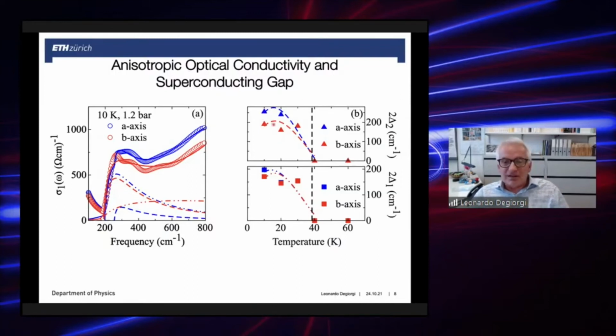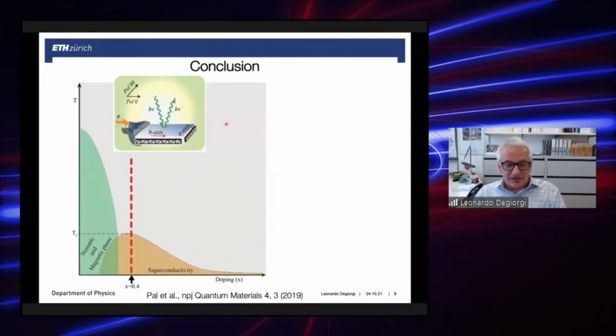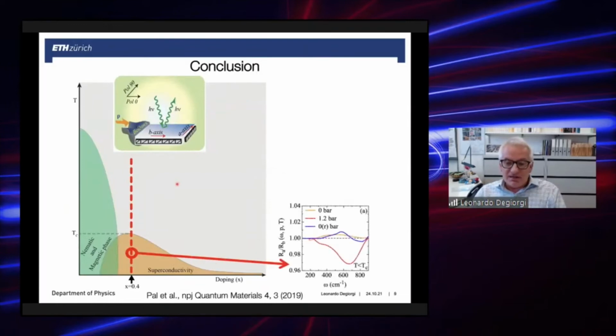That anisotropy is particularly pronounced for the largest gap of the two in these materials. So let me now try to approach the conclusion of my presentation, since I think I just have 20 minutes. Today I focus the attention on this optimally doped regime, for which we did discover a rather important anisotropy at a very low energy scale, in the far infrared, very close to the Fermi level.